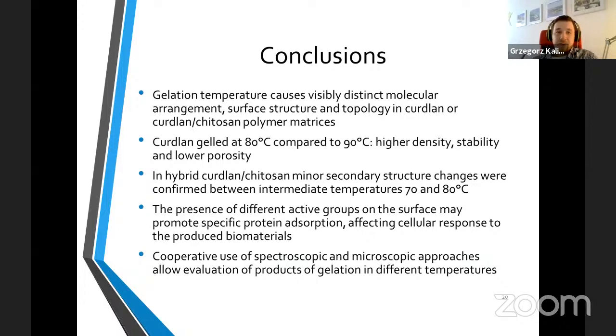In our hybrid, minor secondary structure changes were confirmed between intermediate temperatures, 70 and 80 degrees. And as I mentioned, the presence of different active groups on the surface may promote specific protein adsorption, affecting cellular response to the produced biomaterials. It may be useful in wound management, but also, as already mentioned, biomaterials used in bone substitution. And the most important for us was that cooperative use of spectroscopic and microscopic approaches allows evaluation of products' gelation at different temperatures.